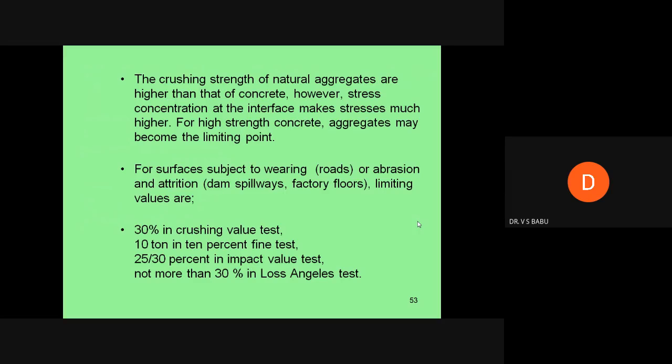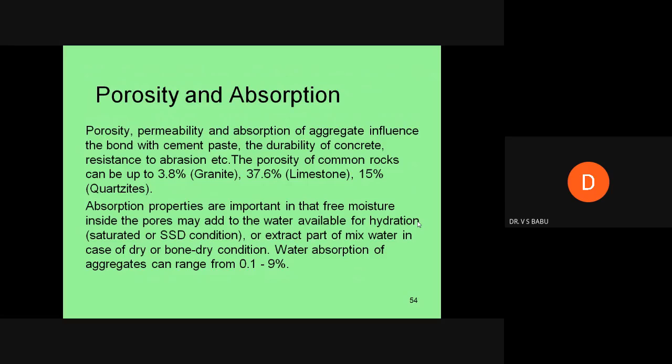Limiting values are 30 percent for crushing value test, 10 ton for 10% fine test, and 25 to 30 percent for impact value, not more than 30 percent Los Angeles abrasion for wearing courses, roads, dam spillways, factory floors, and railway platforms.